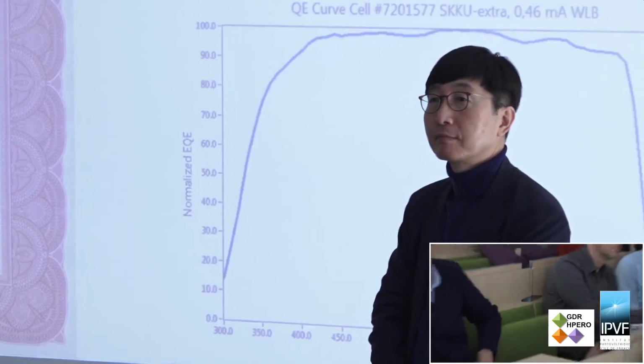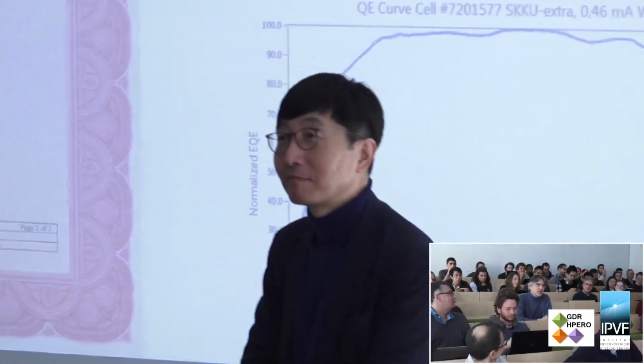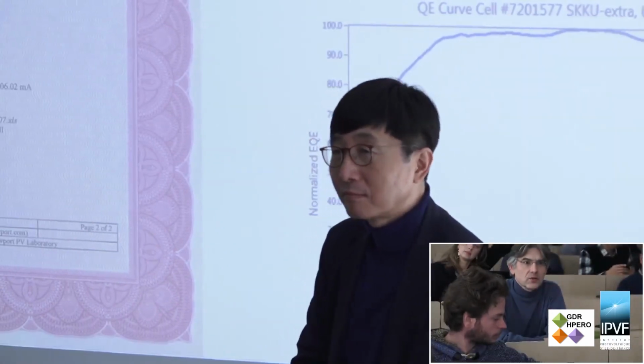Other questions? Oh, okay. You mentioned that a small addition of cesium helped the stabilization of formamidinium lead alpha phase. At first sight, this is surprising for me because cesium also has a room temperature, non-perovskite delta phase. So what do you think is the mechanism in this case, and maybe also in other cases like rubidium? Is it related to some local constraint, the fact that the lattice parameter is different, and then this helps stabilize?